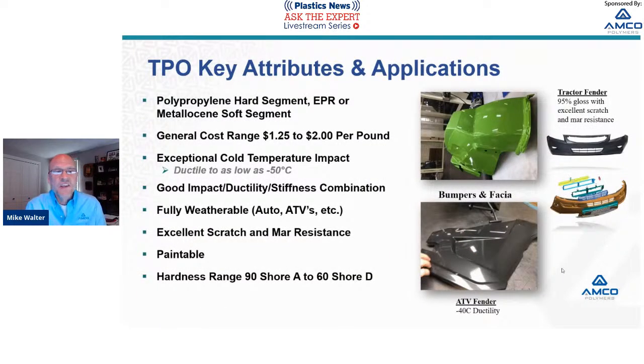Next on the list is TPO, or thermoplastic polyolefins. They have a polypropylene hard segment and an ethylene propylene rubber or a metallocene soft segment. General cost range is $1.25 to $2 a pound. The main reason why you use TPO is exceptional cold temperature impact. We have grades that are ductile down to as low as minus 50 degrees Celsius. So just an overall excellent combination of impact strength, ductility, and stiffness.